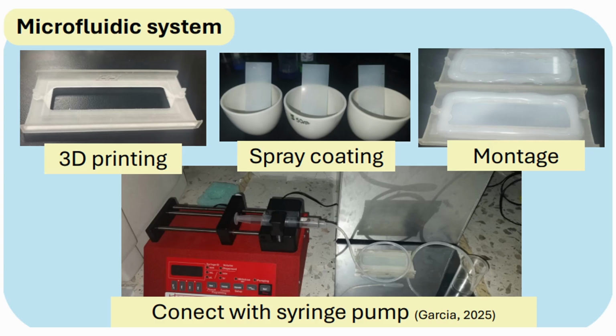The design of the microfluidic system was made by 3D printing lithography using UV resin as precursor. Then, the material was deposited as a thin film on a borosilicate substrate. With the help of silicone, we mounted the system avoiding leaks and created a single-channel laminar system. Through it, we passed the contaminant in the presence of light to complete the photocatalytic test, with the help of a syringe pump and tubes.